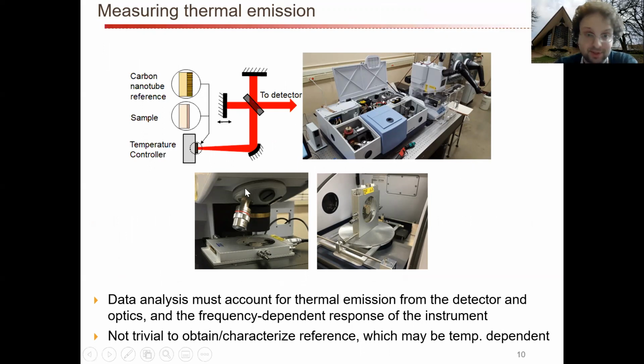It sounds like you should just take your sample and stick it on a temperature controller and send the output to a spectrometer, which in our lab is an FTIR because we're working primarily in the infrared. And then you just capture the spectrum and call it a day. Maybe you change the angle of the sample using, for example, a rotation stage like this, and then you have all the information you need. However, what we found, and of course what has been known in the literature as well, is that this is very difficult to do, especially under certain circumstances.